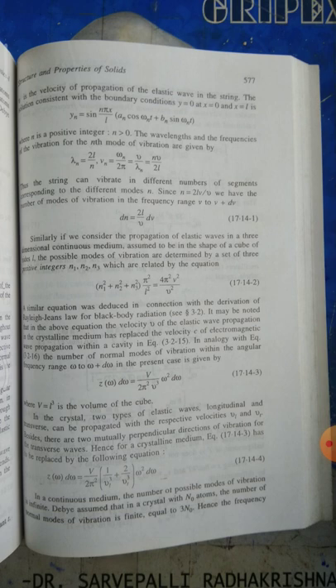A similar equation was deduced in connection with the derivation of the Rayleigh-Jeans law for black body radiation. It may be noted that in the above equations, the velocity v of the elastic wave which propagates in the crystalline medium has replaced the velocity c of electromagnetic wave propagation within a cavity, in analogy with those equations. The number of normal modes of vibration within the angular frequency range ω to ω + dω in the present case is given by Z(ω)dω = (V/2π²v³) ω² dω, where V = L³ is the volume of the cube.